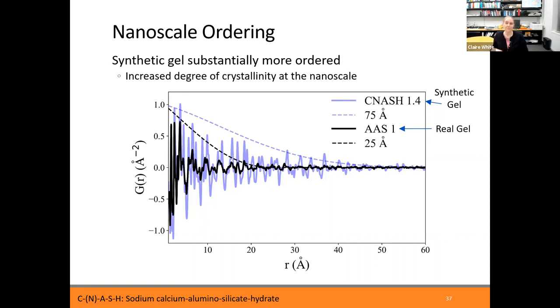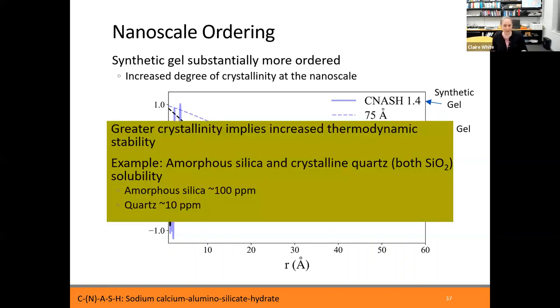So for example, because I know I've kind of twisted this up a bit, let's use an example. Greater crystallinity implies increased thermodynamic stability. And let's use silica as the example here. If you have an amorphous silica versus crystalline quartz, and you look at their solubilities, the amorphous silica is 10 times more soluble compared to the quartz.